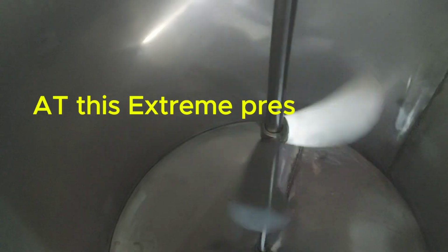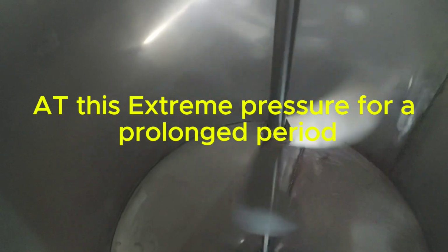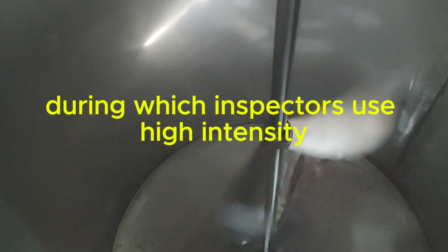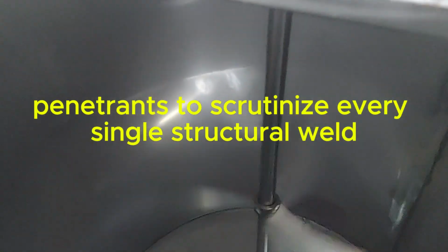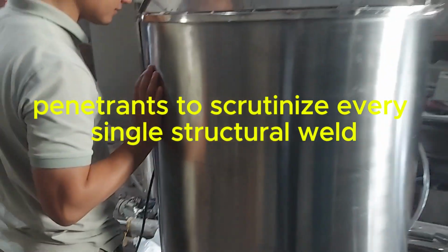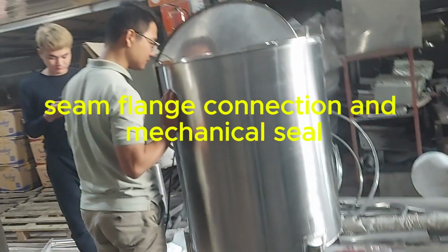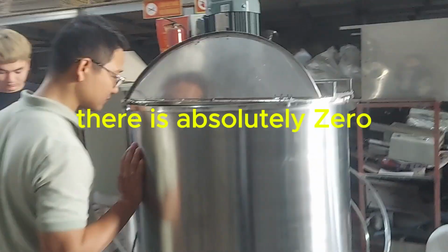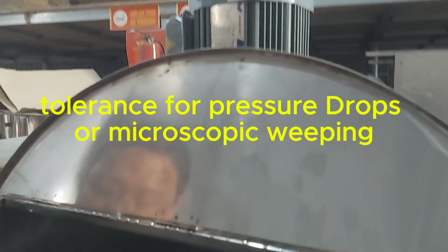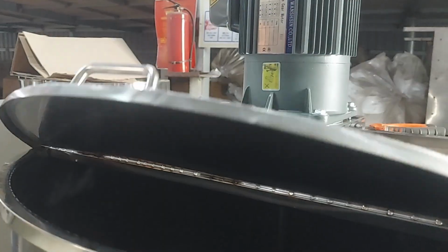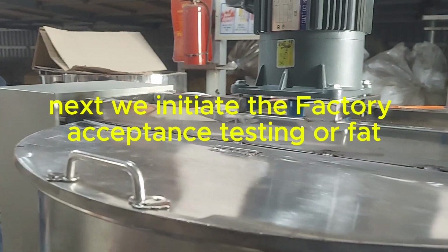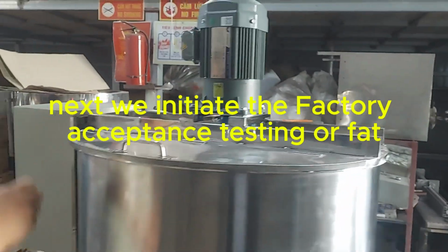The tank is held at this extreme pressure for a prolonged period, during which inspectors use high-intensity ultraviolet lights and dye penetrants to scrutinize every single structural weld seam, flange connection, and mechanical seal. There is absolutely zero tolerance for pressure drops or microscopic weeping. Next, we initiate the factory acceptance testing, or FAT.